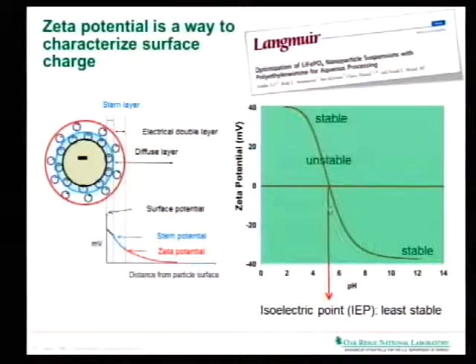The way of characterizing that, the way of understanding where my particle surface is in this scenario, is measuring Zeta potential. The Zeta potential is the surface charge you have on your particle, and whenever your Zeta potential is somewhere in this region, lower than 20 or higher than minus 20 millivolts, you're in an unstable region. Your surface charge is not sufficient to repel the particles from each other. Whenever you have charges above 20 or below minus 20 millivolts, you're able to keep them afloat. You're able to keep them apart from each other.